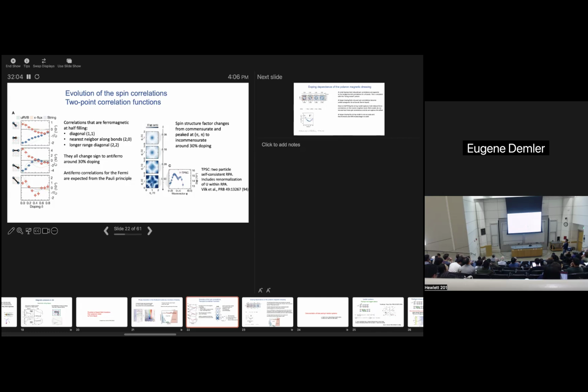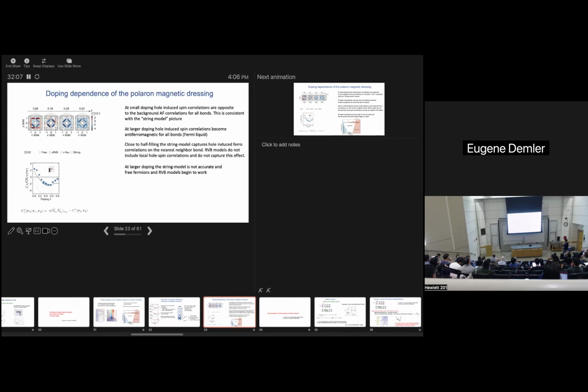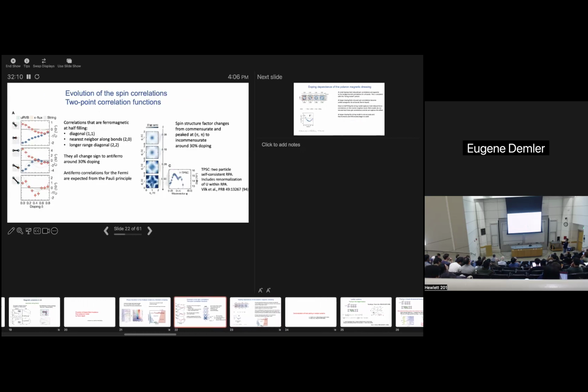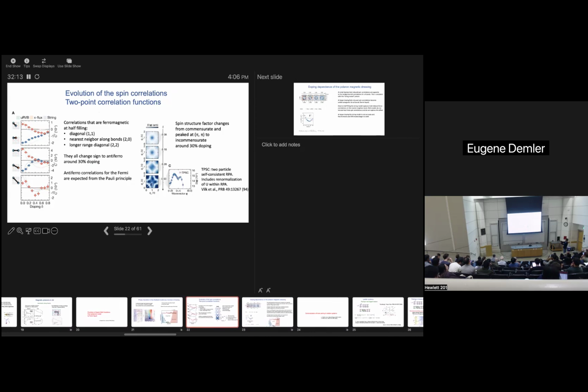And in fact, antiferromagnetic correlation is something that we would expect based on the theory of simple metals. It's just the Pauli principle: if we have weakly interacting fermions, we cannot find two fermions with the same spin on the same site, although we can do so for fermions with opposite spin. That's why we're more likely to find fermions with the opposite spin next to each other. So we find that at least large doping is indeed consistent with our expectation of what spin correlation should look like. Whereas at small doping, it's more reminiscent of what we find in a Mott insulator.